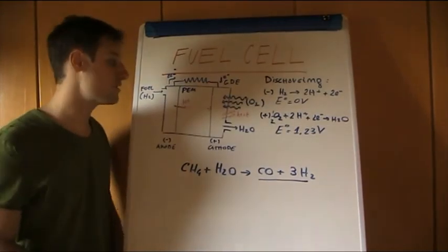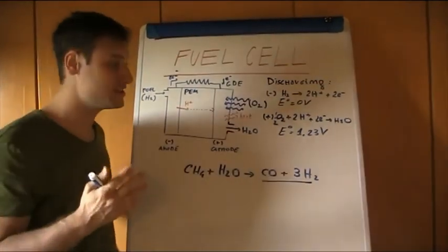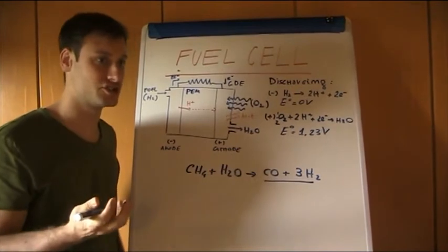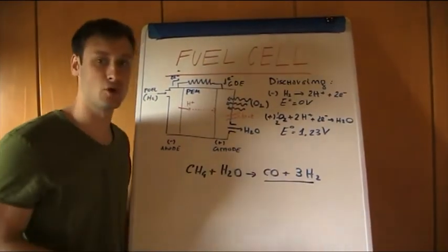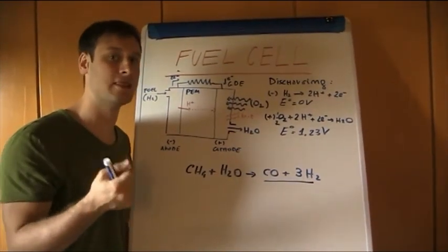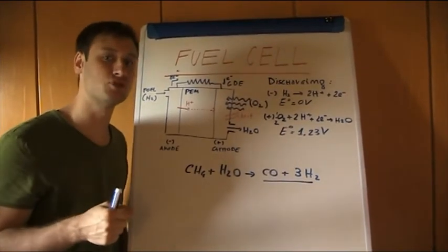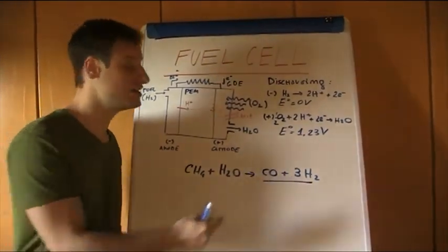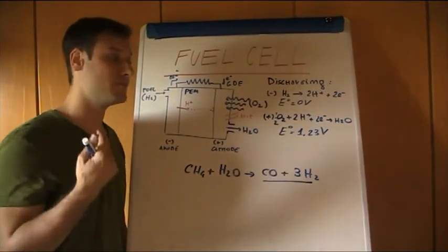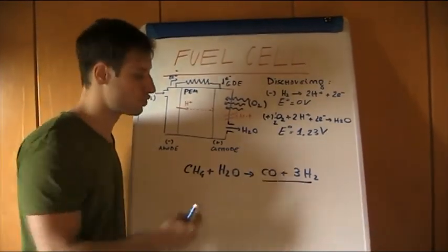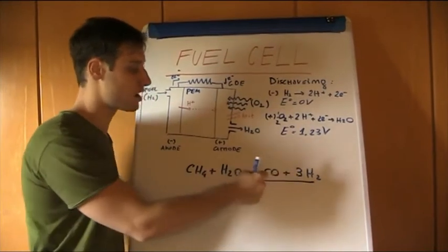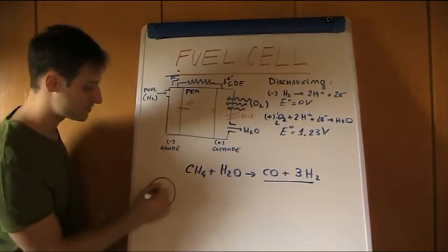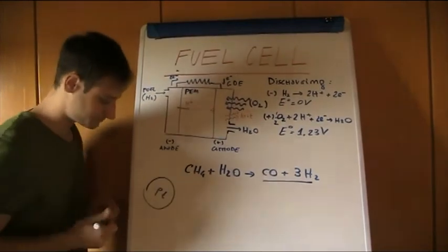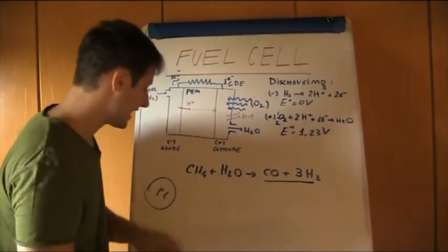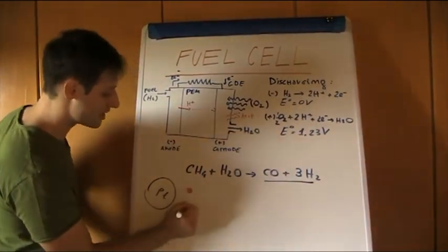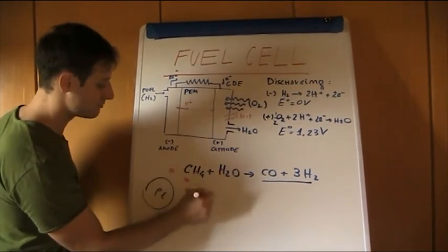This is a really huge problem because platinum is extremely interactive with CO. The carbon monoxide is adsorbed a lot on platinum because the adsorption energy of this species on platinum is higher with respect to hydrogen. And so the platinum prefers to allow the adsorption of CO with respect to hydrogen. If we have, for instance, particles of platinum and we have particles of hydrogen here, the red ones represent hydrogen particles.